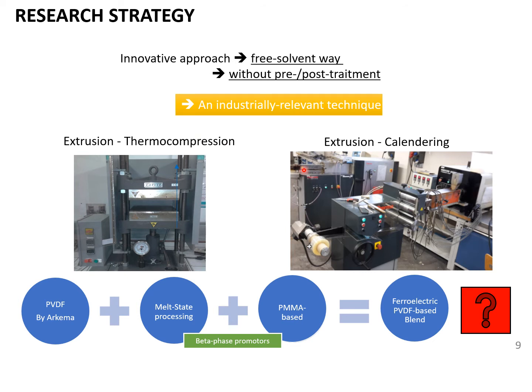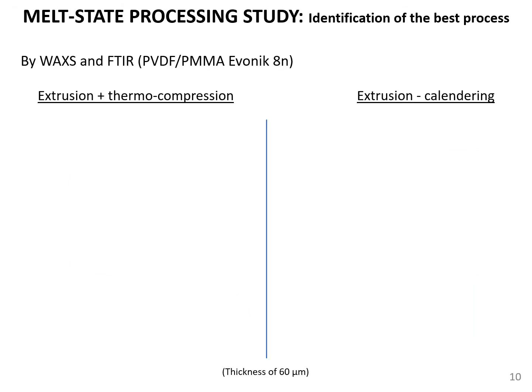Two post-processing techniques were investigated: thermocompression as a static approach, and a continuous approach based on the calendering technique, in order to produce continuous films that you can directly obtain with piezoelectric properties, which I will show in a few seconds. To identify the best process in terms of crystallization, we use two techniques: WAXS analysis and infrared analysis based on this blend. We make a comparison on films with a thickness of 60 microns.